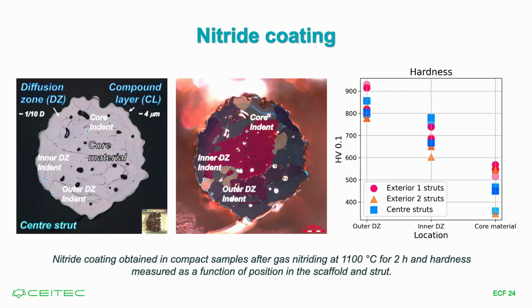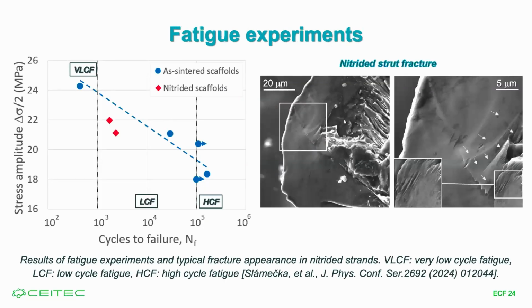So then we tested them under fatigue, and as you can see, with limited number of samples, these were not so good as sintered scaffolds, but given that this is really on the verge of low cycle fatigue region, this is actually good results. And the reason why they were not so good, and there are other studies, is that this nitriding layer is brittle, so after it fractures, it introduces large initial crack, and the fatigue life is worse.